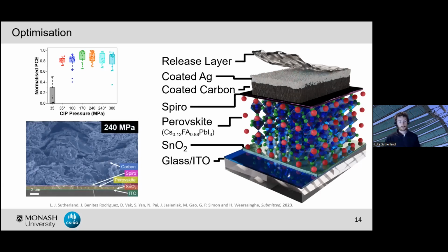Finally, 240 megapascals, really immense pressure, but we were able to see this seamless connection between our carbon and underlying spiro, which if we look at the normalized power conversion efficiency, we're able to see results in our highest performing devices there.